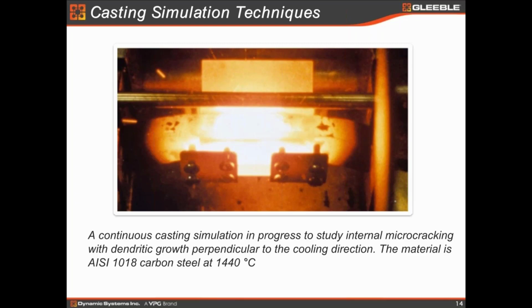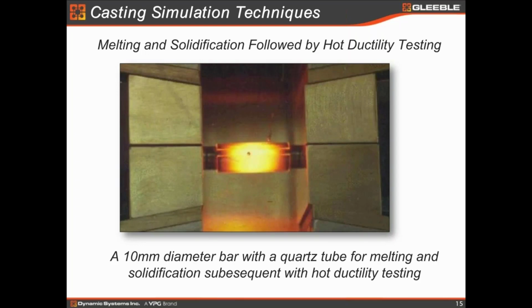Okay. But the most popular way that our Gleeble users have been using is really this testing technique. I would rather really call it the Dr. Suzuki methodology, because this methodology was developed at Nippon Steel in the early 1980s, who used really a 10mm diameter bar, and he used a quartz tube to slide onto the cylindrical sample. And we know the quartz softening point is more than 1500 C, right?